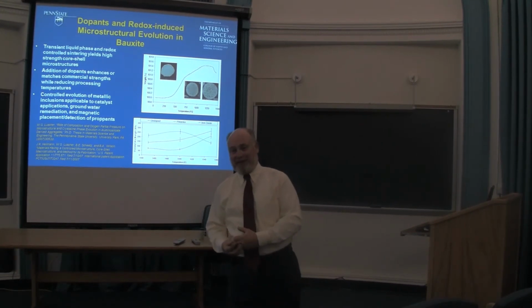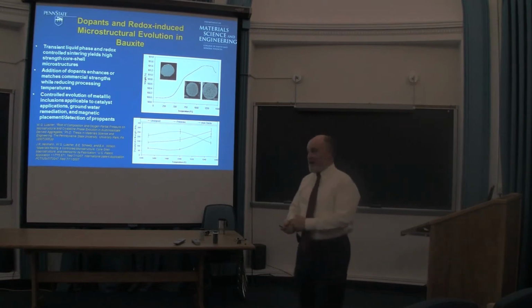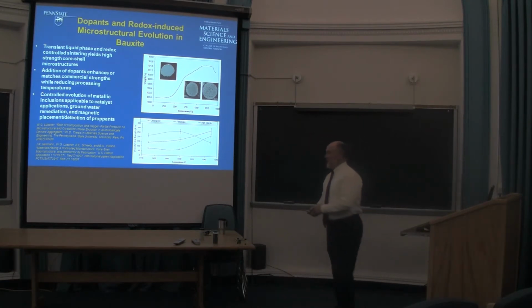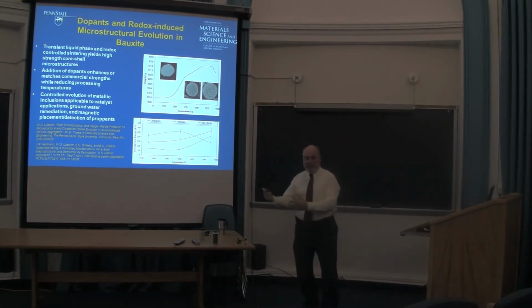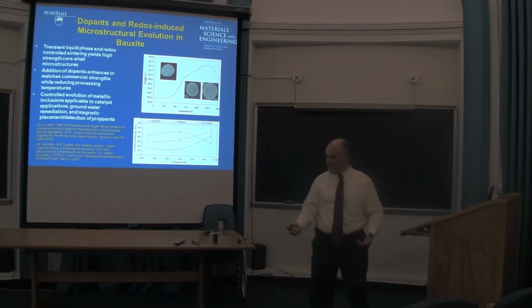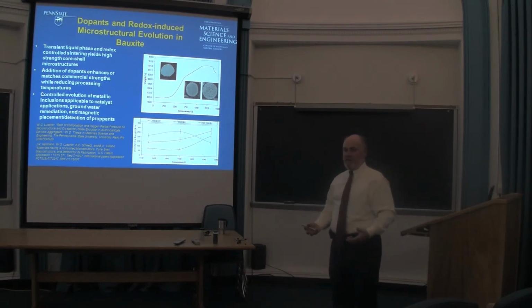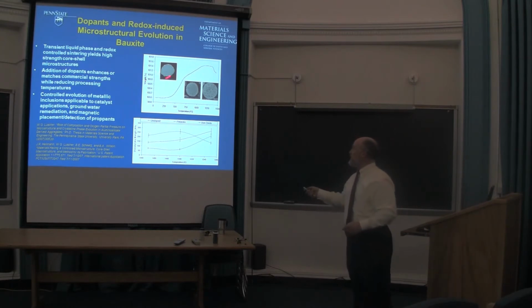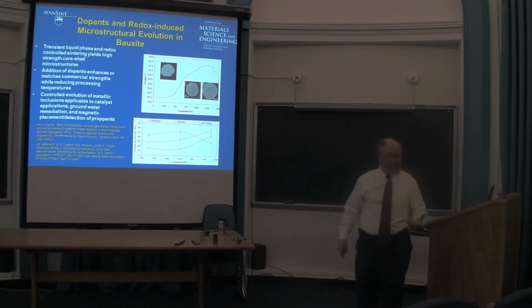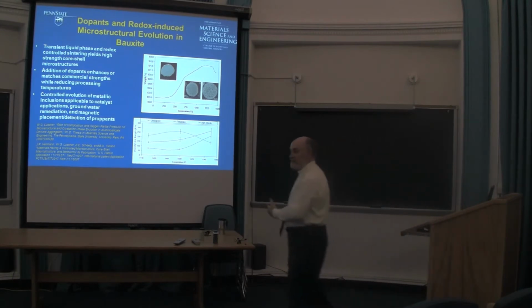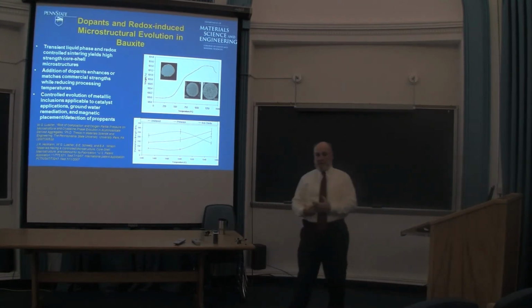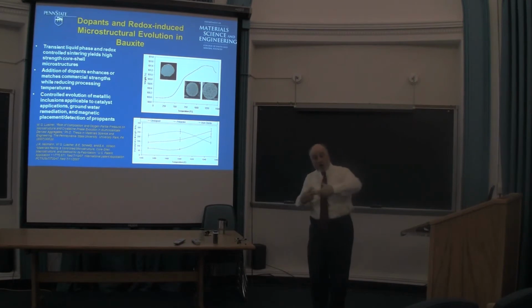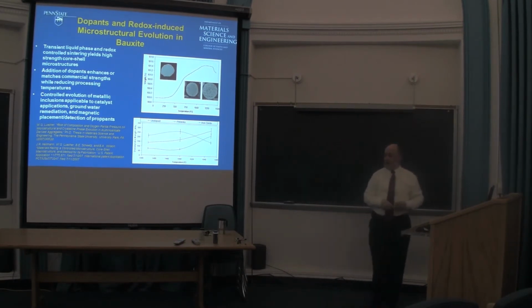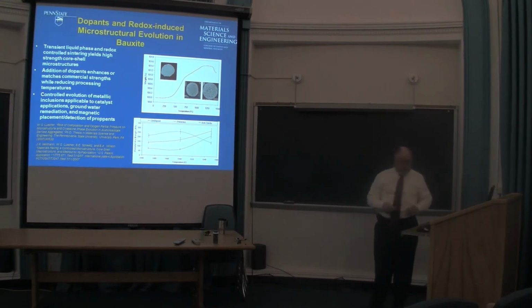I know a lot of stuff they use, right? And so do they, right? So the bottom line is, if you can use less of some of that stuff, maybe you'll have less of a concern with the hydrofracture, okay? And if you can treat what's down there with a catalytic surface on your proppant, you don't have to treat the water as severely when it comes to the top after you've hydrofracked, because you have to remove your water from your hydrofrac well, at least some of it. Okay, you get about, what, 40% flow back these days, 20%?